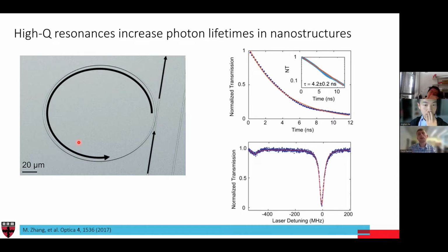And if you were to take the Fourier transform of this transmission, what you would find is that you have these very narrowband resonances that appear in the transmission spectrum that are defined by a quantity that I'll talk about called Q, or the quality factor, which is defined as the wavelength of the resonance divided by its line width. In this case, we're able to get quality factors on the order of maybe 5 million, which means that light is trapped inside the structure for an extremely long amount of time. If you back out the total size of this cavity, this means that light will circulate in this cavity tens of thousands of times before actually exiting.